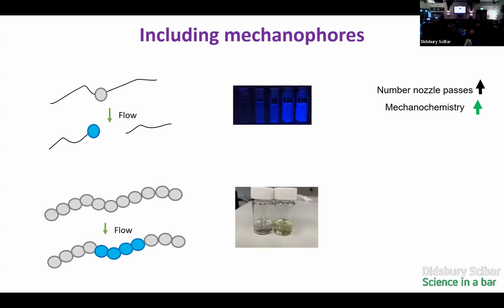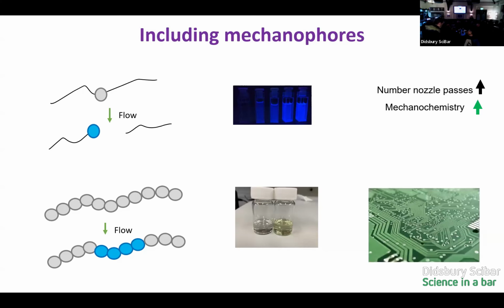But what happens if we move to a system where every repeat unit in the polymer is now a mechanophore? So every single one of these paper clips now has the potential to open and react mechanochemically. And we see that we now get a whole host of mechanophores in the center of the polymer chain activated. And we go from, in this case, a species that's clear, colorless, to something that's yellow. And this is really exciting because not only is it yellow, it's also conductive. So we can start to think about printing different materials and having something that's insulating and something that's conductive printed from the same starting material. And that's really, really exciting.